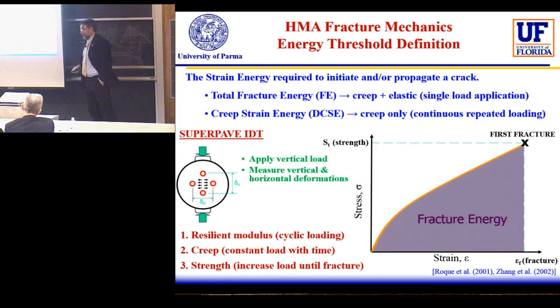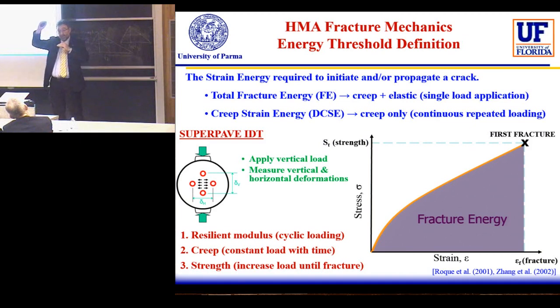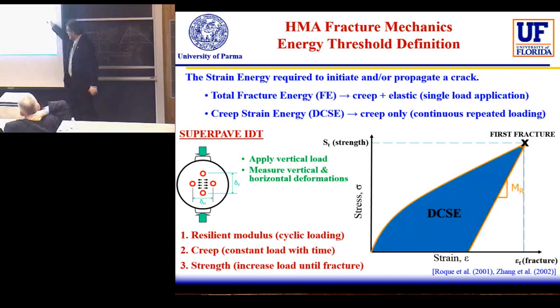So we can define, following what I just explained, the total fracture energy as the combination of the creep plus the elastic part of the energy, something like the area below the stress and strain curve, considering the curve until the first fracture. When the first fracture appears, it means that in that area of the material, the threshold was overcome. And from the fracture energy, using the elastic property, the resilient modulus could be a way to estimate the elastic property, or some other prediction. If you are able to have an estimation of the elastic property, we can take out the elastic component in the stress and strain curve, and we can define the dissipated creep strain energy as this area.